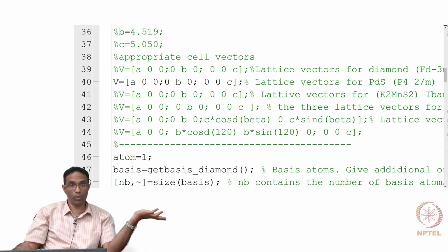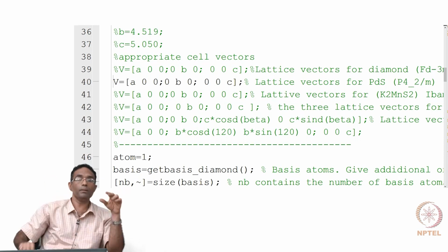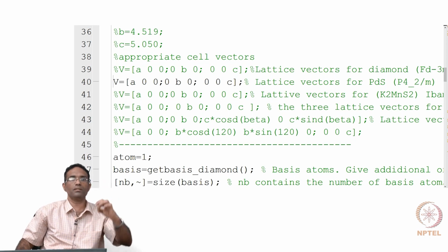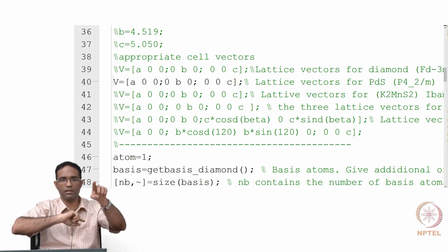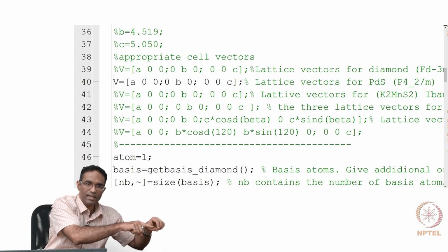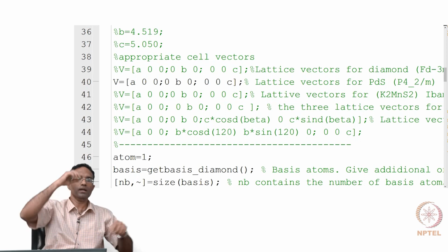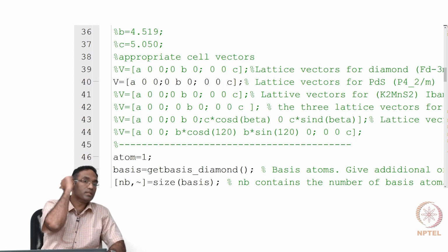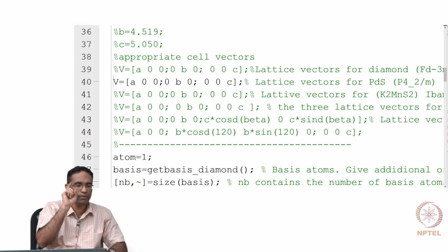It is also possible to have a coordinate system where you look at it from the b axis. For example, in the monoclinic lattice, they would say that the b axis is unique. What that means is, this is a, this is c, and this would be b, the axis which has the twofold coordination. In that case, you would have to associate the y with this b and not with this c. It will make a difference in the final structure that you generate.